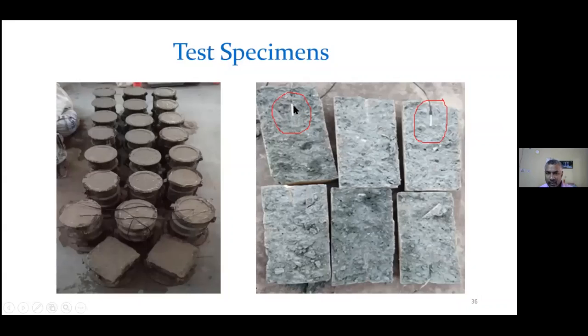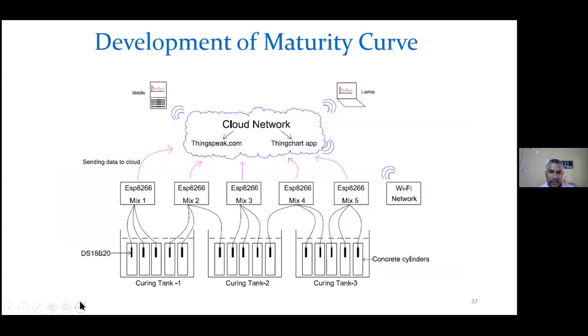And you can see here in the red circle a white colored thing, and here also, that shows the location of the sensor inside the specimens. So it is something like that. In a curing tank, we put the 3 specimens for each mix, right? 3 specimens are giving you the temperature value. So we can take the average of these three data, and from this average temperature value we can find out the maturity, right? The temperature time function maturity.